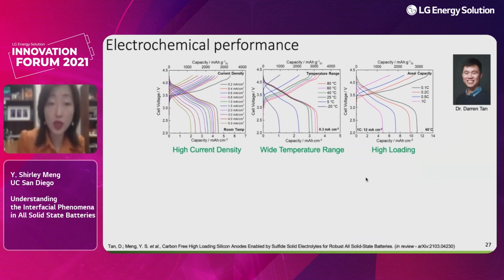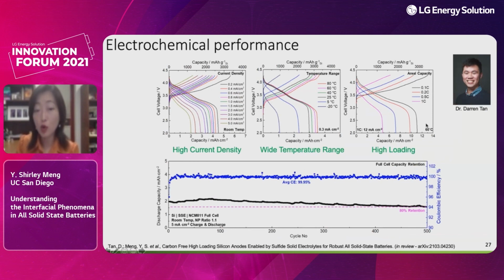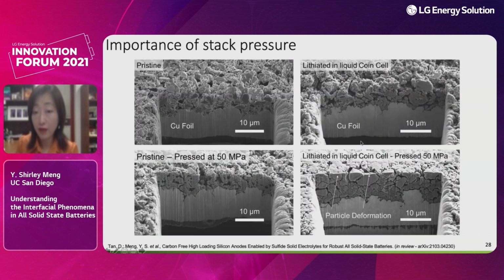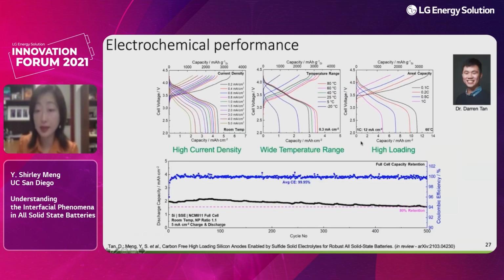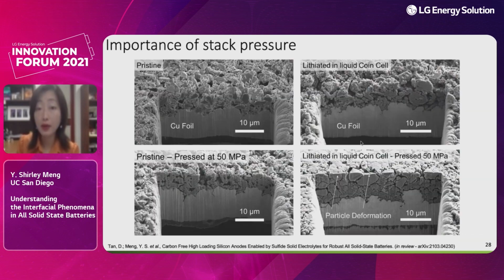In Darren's work, we utilized pure silicon, 99.9% silicon loading with very high area loading, and the utilization rate of the silicon is also very high. We were able to demonstrate a very high critical current density, wide temperature range, and high loading. Of course, this is small laboratory scale testing where we demonstrated 500 cycles, but we think this study opens up a new possibility for how to design solid state batteries.